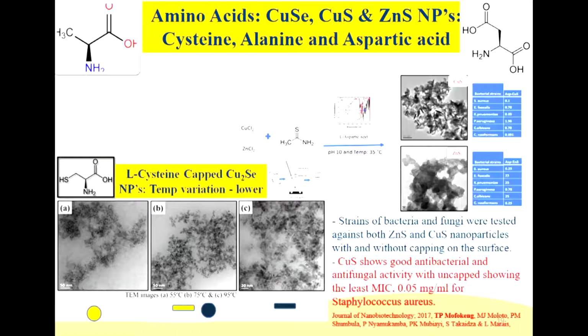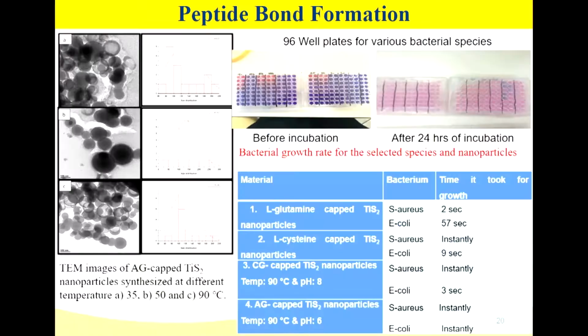In addition, you realize that the MIC values show some signs that, for copper sulfide in particular, there's a greater deal of MIC values being lower compared to the rest, where the activity against the bacteria is starting to emerge greatly. And we explored that even more and asked, what if we combine two amino acids to make a peptide bond formation in them?